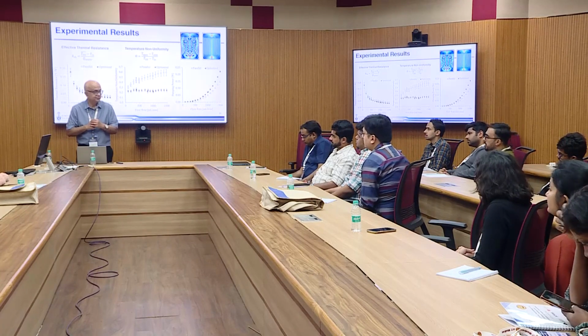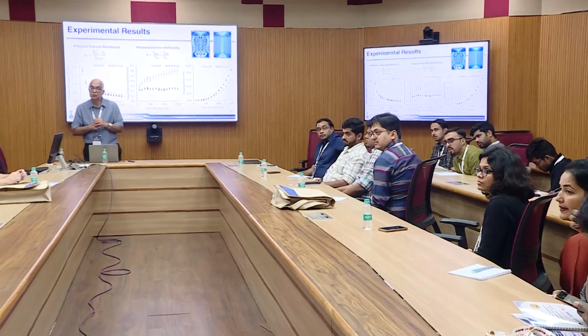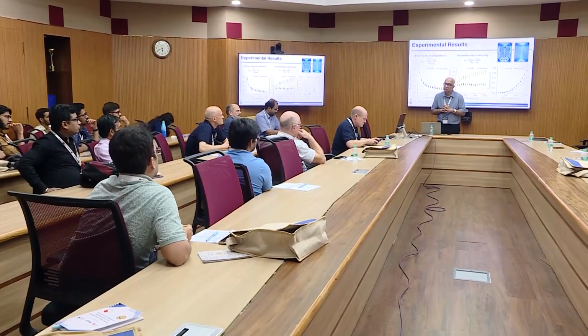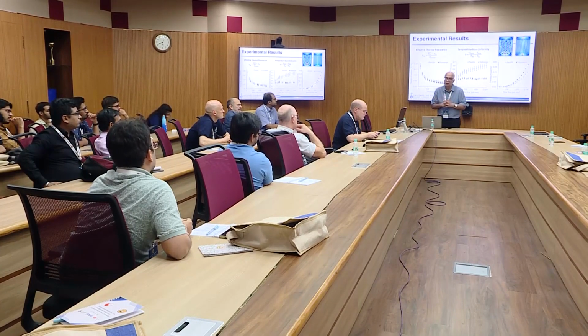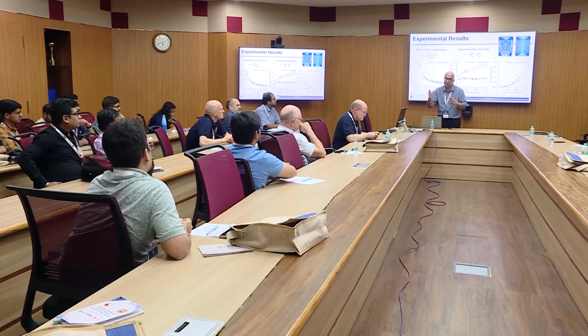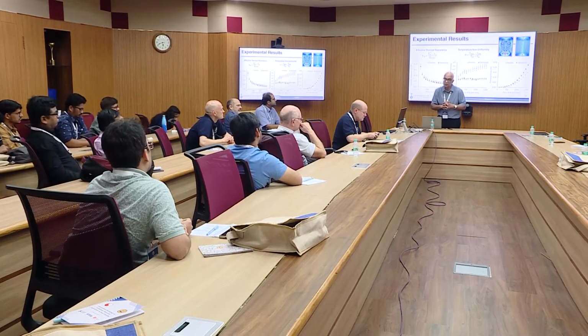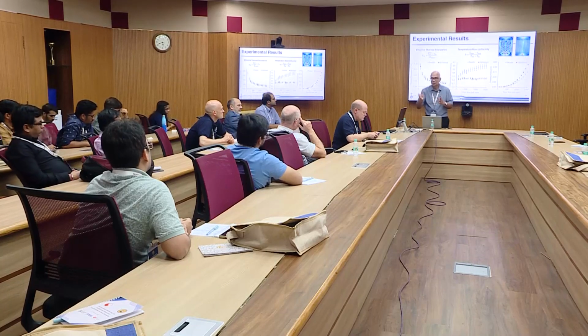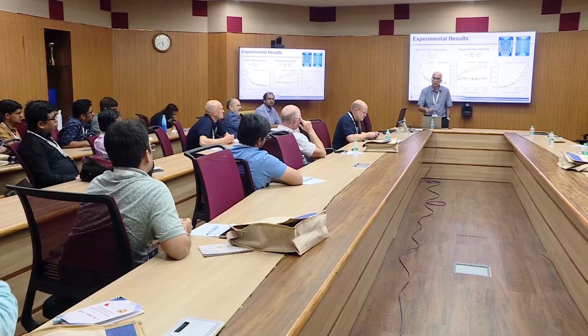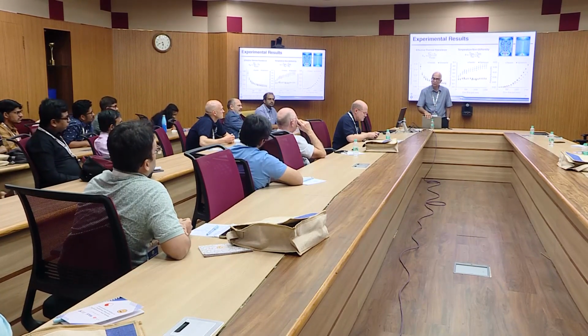And we can coat as big a plate as you want. What liquid pressures have you been tested for? At higher liquid pressures, are there any leakages? We didn't really go to high pressure. There's no real incentive right now to go to very high pressure. I think we tested to 60 psi, which is about 400 kilopascals. But that is ongoing work. We are working with somebody who wants to use it for battery cooling, and we are doing tests at pretty high pressures. I have a student doing precisely that right now. Up to about 4 atmospheres or so, you can go without any problem.